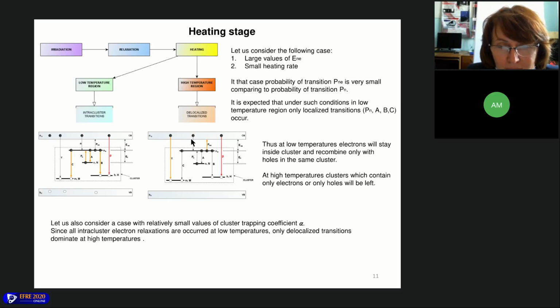We'll divide the whole temperature region during heating into two subregions, low temperature region and high temperature region. It is expected that under such conditions, in the low temperature region, only localized transitions occur since no electrons will reach the conduction band. Conversely, in the high temperature region, only delocalized transitions occur since clusters which contain only electrons or only holes will be left. We are interested in the number of left electrons and holes after the low temperature region.